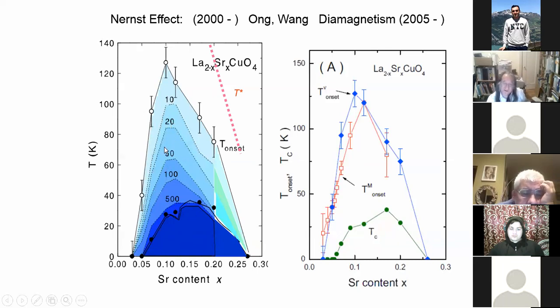So this is still a region where the material is not completely superconducting, but something like that shows up at this high temperature. And it is also found in diamagnetism. Diamagnetism is a small expulsion of the external magnetic field, which is again reminiscent of the real superconductivity effect. And that happens at rather high temperature in the normal state above the transition temperature. So this is something not expected in the standard superconductivity theory of Bardeen, Cooper, and Schrieffer. And this is new.